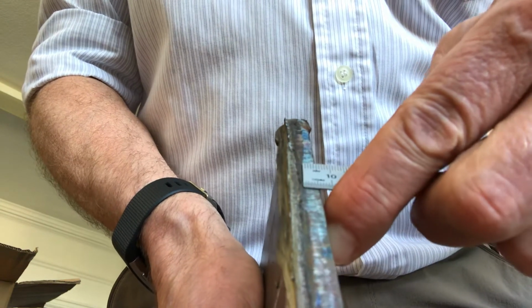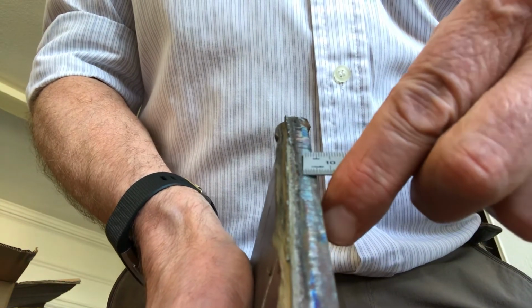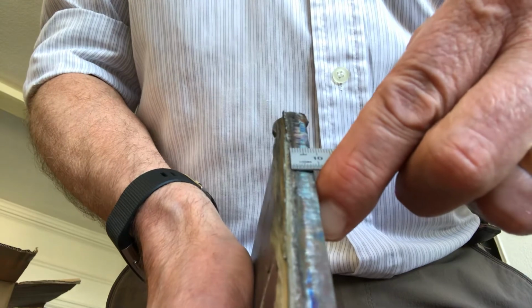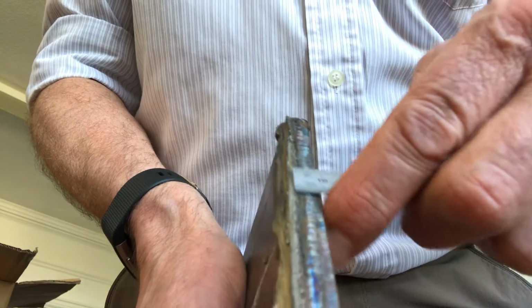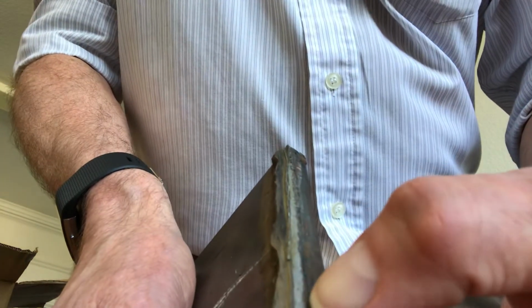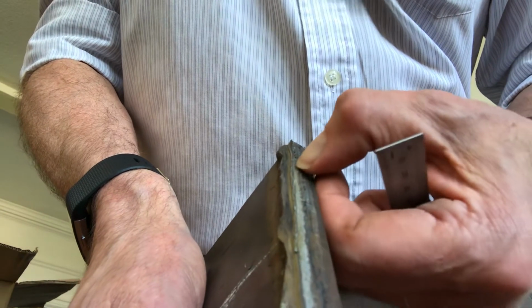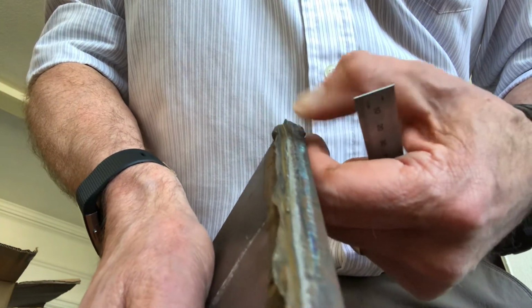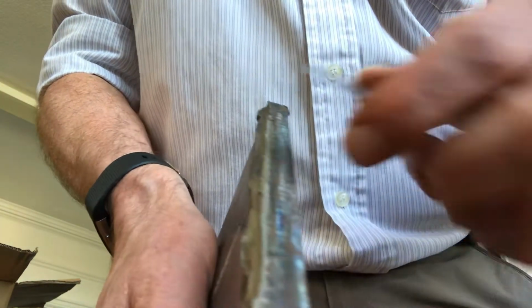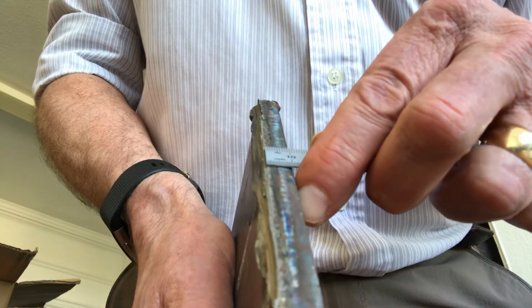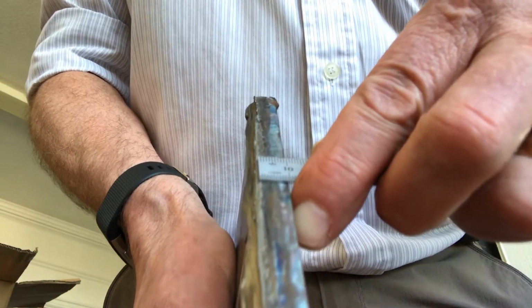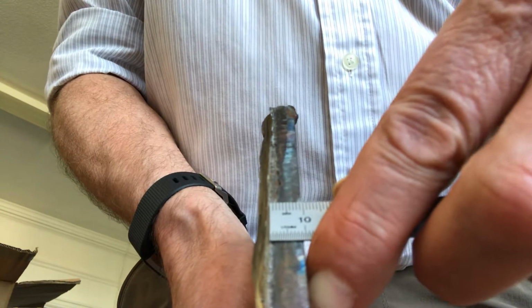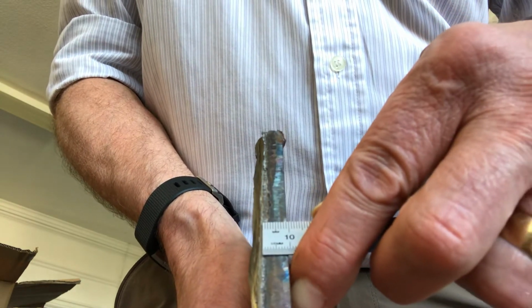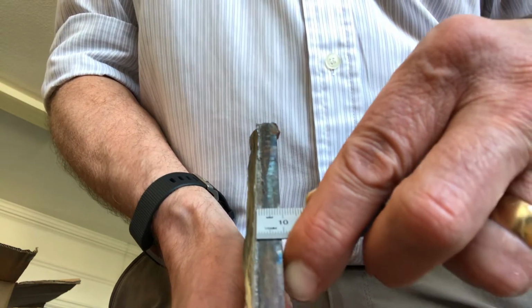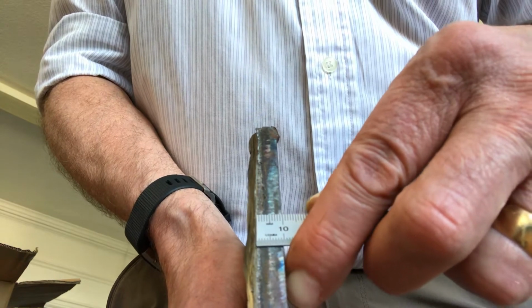And what we're looking for is the point at which that thickness meets the weld. And as you can see, although there is some burning of the edge there, the actual fracture surface, which is the one that we're interested in, and bearing in mind we cannot see the edge of the plate, that's a very important thing to note. If you can see the edge of the plate, the chances are it hasn't fused properly. And that dimension there, like so, is the thickness of the plate or less. And that's the important thing.